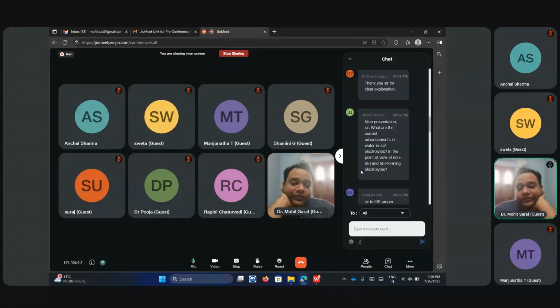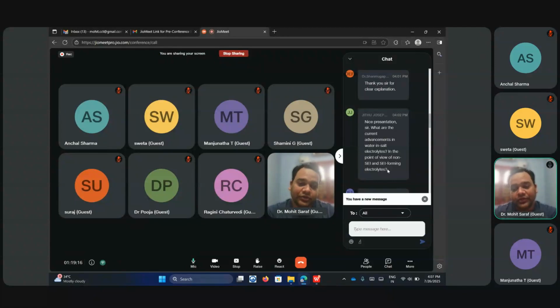Now, whether it is from the point of view of non-SEI and SEI forming electrolytes, in most cases, whether it is water-in-salt electrolytes or any other kind, if SEI formation is there, most likely you will get an expanded potential window. So if you design your electrolyte such that you do not lose your ionic conductivity, since there is a lot of solute ions, while at the same time expanding the potential window, I think that would be a perfect case for both SEI and non-SEI forming electrolytes.